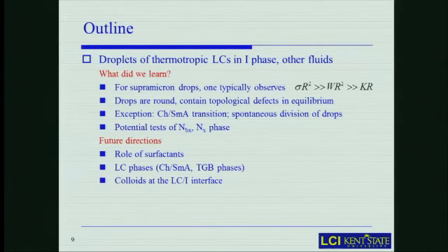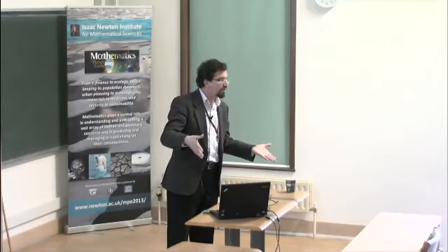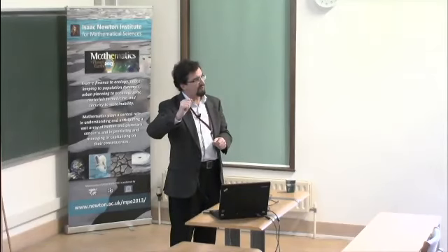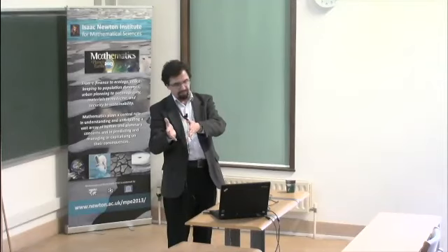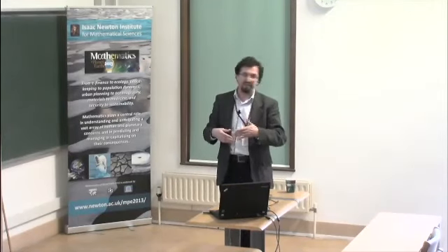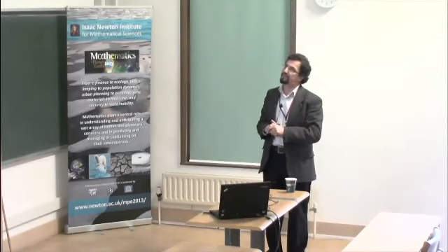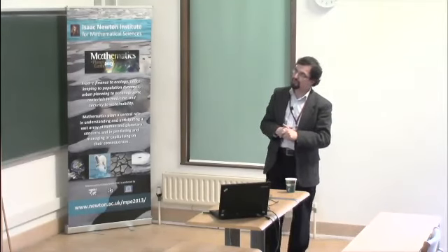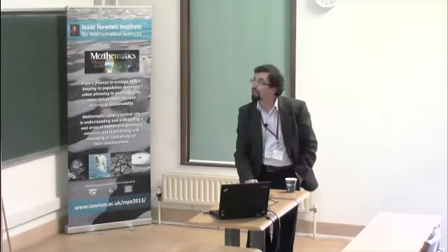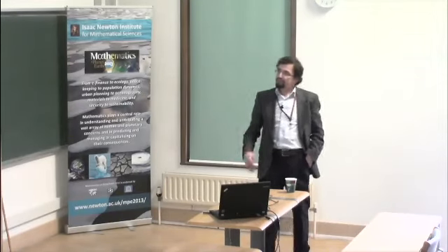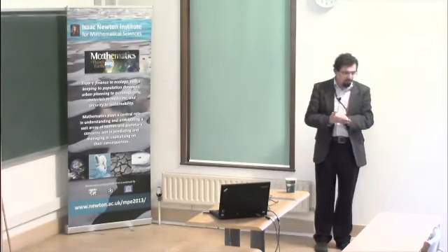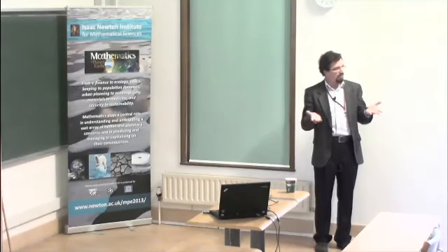And besides the practical applications, by the way, that I failed to mention, droplets of liquid crystals have been used in polymer dispersed systems, and you can use them as a kind of electrically switchable fog. You apply electric field, you realign the liquid crystal droplets, and the transparency of this polymer dispersed system changes as a result of the applied electric field. But you can also use them for tests of the existence of the biaxial phase, and who knows, probably also the Nx phase.